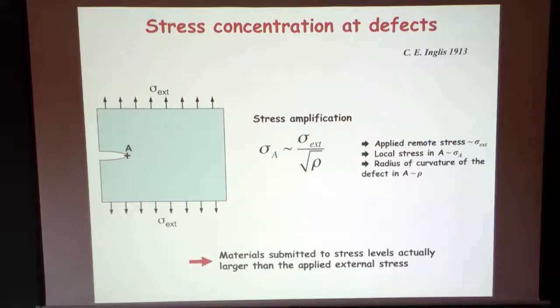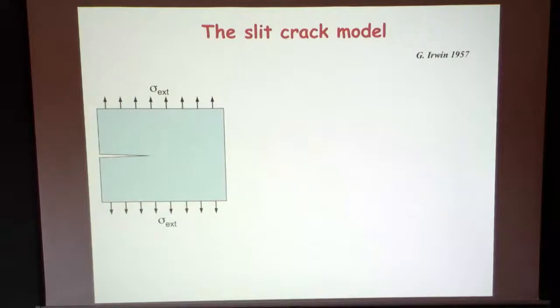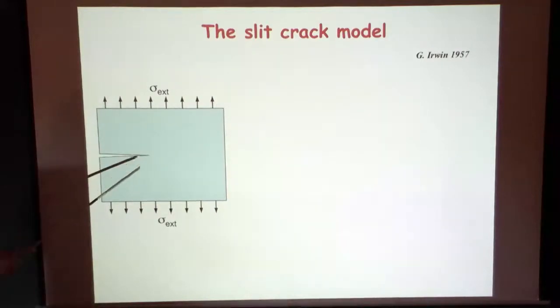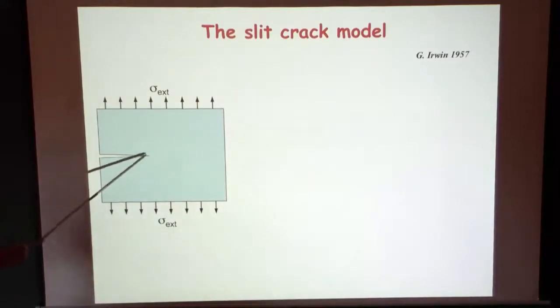Okay, so you see there is a high dependency on defects, and you want to somehow develop a model that is not so dependent on defects, and ultimately such a defect will lead to the most catastrophic defect you can imagine in your system, a slit crack, because then the radius of curvature goes to 0 and the amplification is maximum. So nature is made this way: you always end up with the worst defect possible in your system.